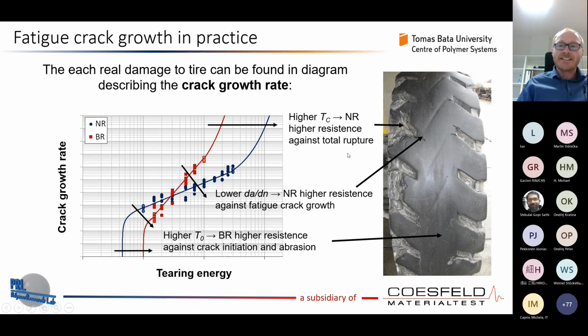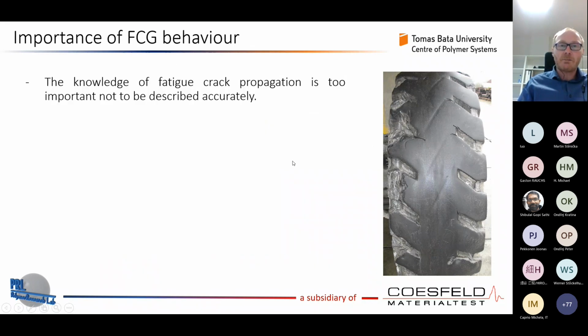And even for TC, that means cut and chip behavior, for example, for the real application in a tire, that means we need to use natural rubber compared to butadiene rubber, while natural rubber, due to strain-induced crystallization, will provide the highest resistance against such a cutting process. Those are very quick crack growth processes. And compared to butadiene rubber, once there is some crack propagation, it will immediately propagate close to TC, and we will never be able to stop it.